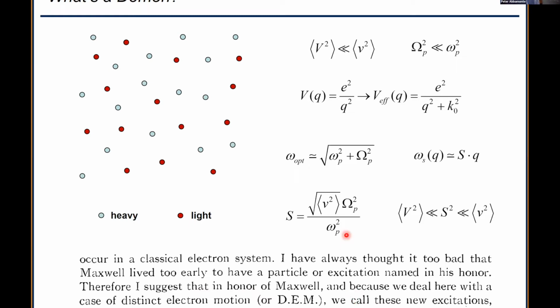And what this paper shows is that if you have a system of 2 different charge carriers, let's say light electrons and heavy electrons, this could happen in a plasma, it could happen in a material with 2 different Fermi surfaces, then what you get are 2 plasmons. And if the conditions are right, one of those plasmons can end up at 0 frequency. So the way he considered it is each of these 2 baths of carriers would independently generate a plasmon. And if one of the baths is very light, the other one is very heavy, those 2 plasma frequencies will be very different. And so he called them capital omega, lower omega p.